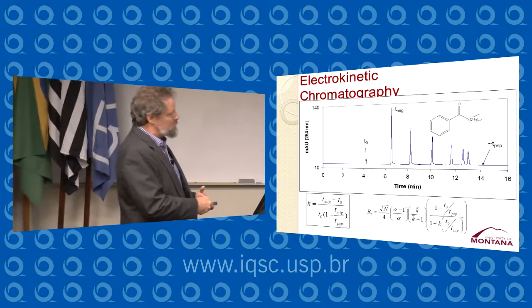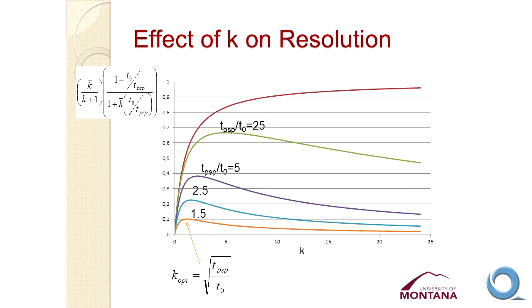This equation tells us that what we need to get good resolution is a large number of theoretical plates or high efficiency, and electrokinetic chromatography affords us that. We generate typically a few hundred thousand theoretical plates using this technique, so that's very nice. We need to have good selectivity, and we need to optimize our retention factor term. And this set of plots shows what the effect of retention factor is. Plotted on this axis are those last two terms in the resolution equation, the retention factor terms. And then on this axis is the retention factor.